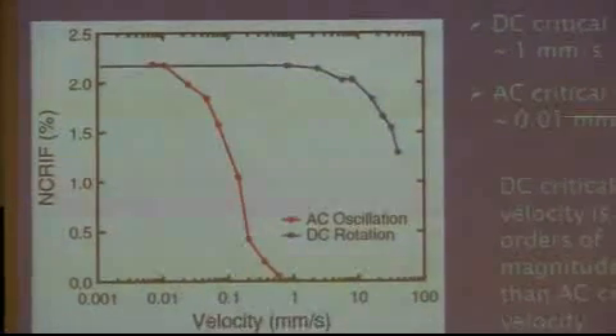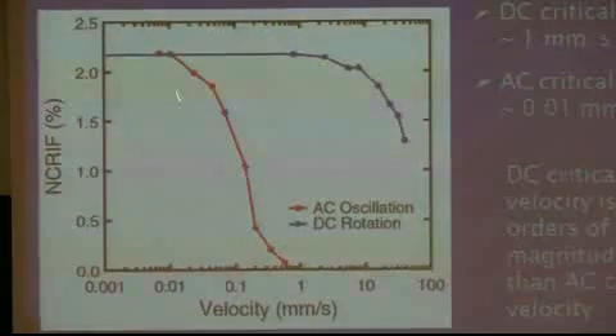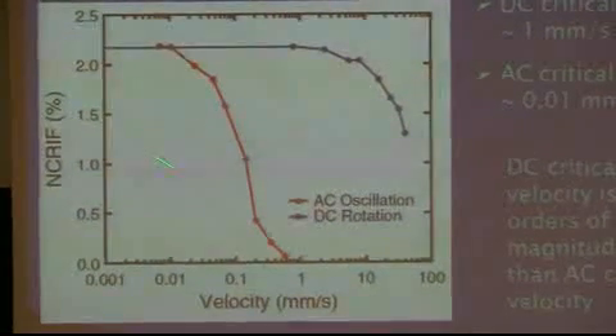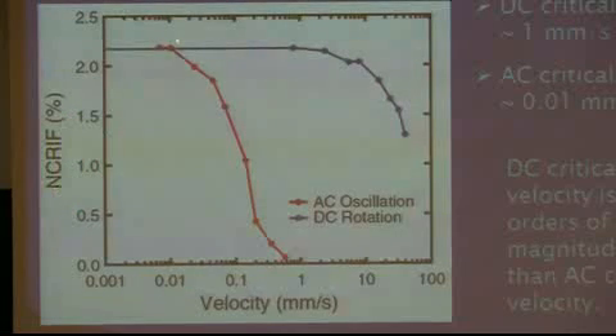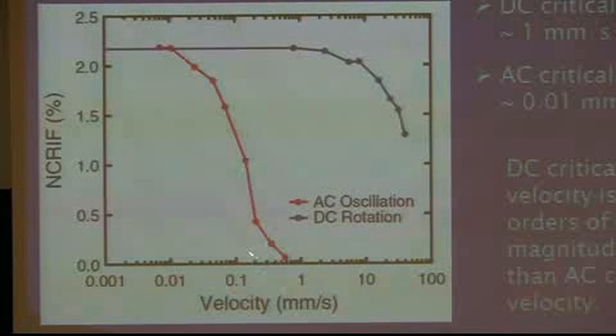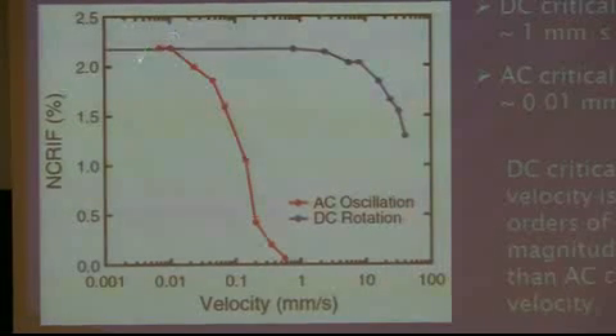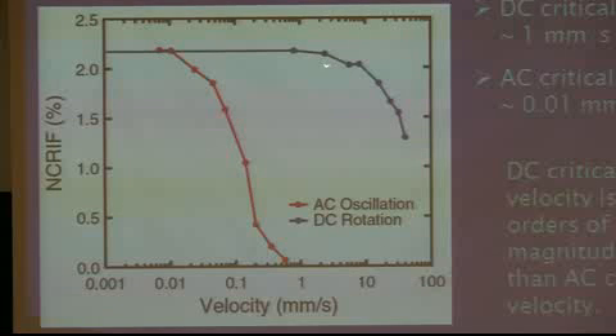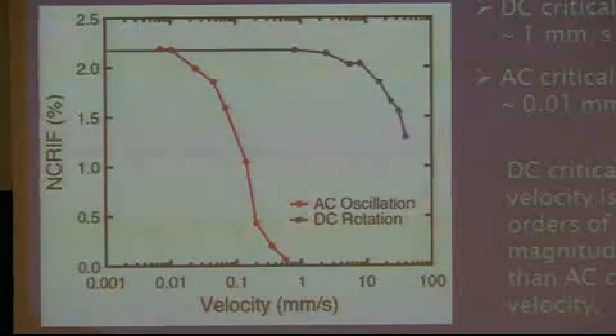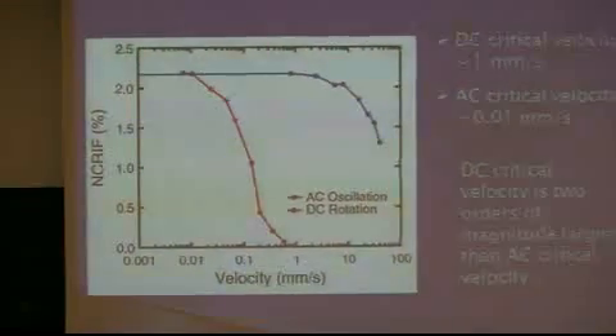Another difference comes from the critical velocity. If you use the AC oscillation, you can suppress the non-classical rotational inertia like that. However, the critical velocity showing this kind of suppression is two orders of magnitude smaller than DC rotation induced suppression. So AC and DC are quite different.